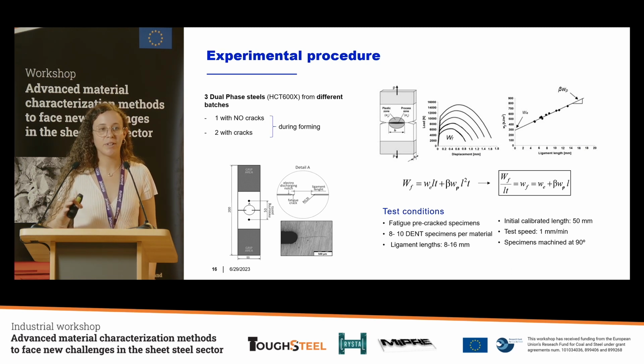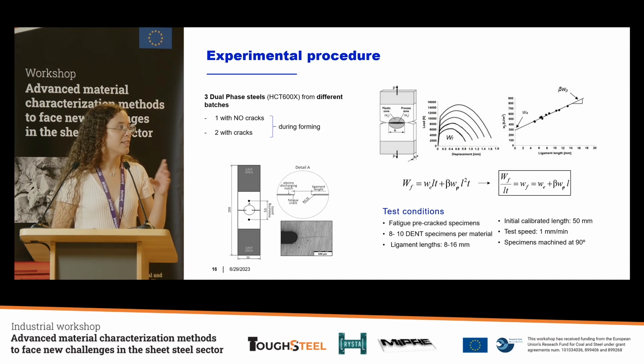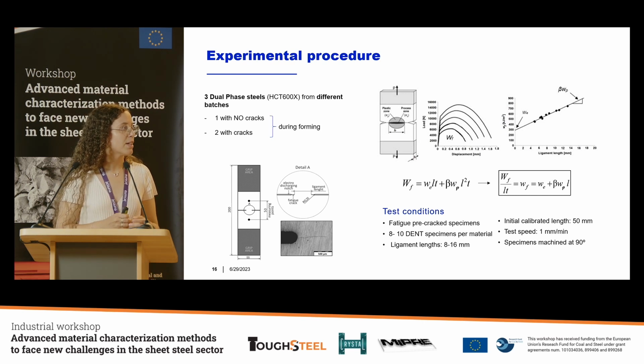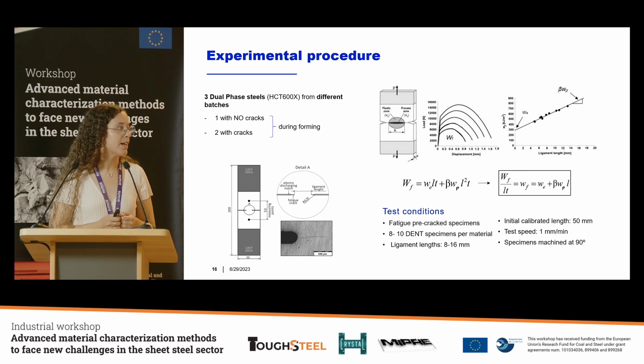You probably already know what it consists of, because if you have been following this project, you may have seen this method already. But basically, with this method we can separate the energetic contribution of crack propagation into two terms. One is the essential work of fracture energy, related to the energy needed to create 2 new cracks in a material. And the other part is the plastic work, which is related to the deformation around the crack